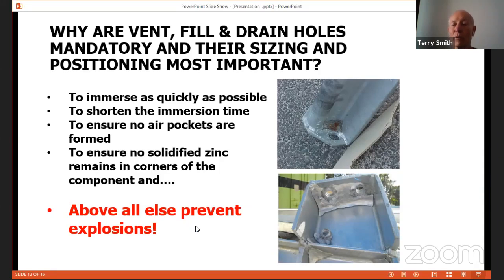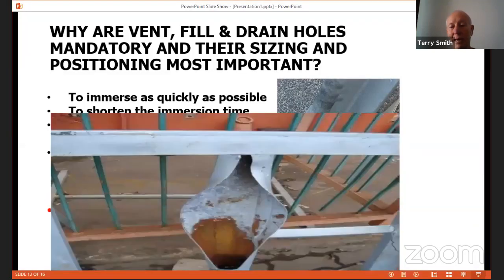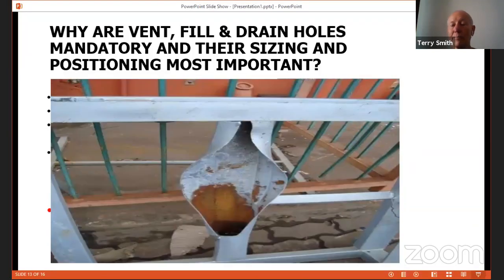Now, generally, if you have any moisture contained within an item that is being galvanized, as soon as it hits the bath, that moisture changes into superheated steam, which has a volume change of 1 to 1700 times in volume. And this is basically what happens. It's extremely dangerous, not only to the galvanizer, where this can certainly maim or kill people.